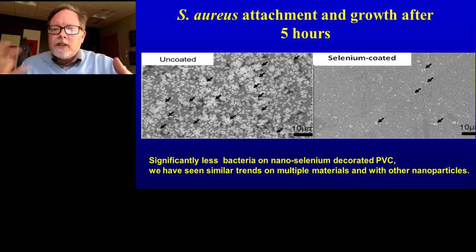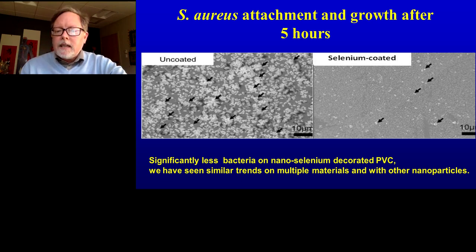Here's a great picture that describes it all too. We've done this for polyvinyl chloride. PVC is a common polymer used for catheters. You can see on the uncoated polyvinyl chloride catheter, millions of bacteria, and these are Staphylococcus aureus, have attached to this PVC. The simple coating of selenium on there significantly reduces bacteria attachment and growth. And again, this is not using an antibiotic.